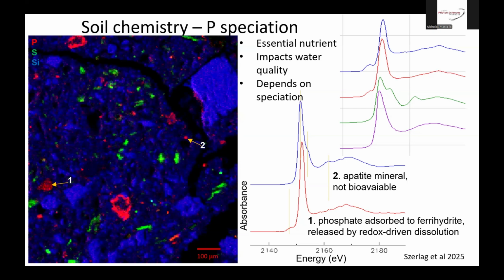So the grain marked 2 is the mineral apatite, so it's a mineral grain, so it's relatively inert, and it will not be bioavailable, and it won't wash away very easily. But the one labeled 1 is more diffuse, and that's actually phosphate adsorbed to ferrihydrite, an iron mineral. And you can see that there's a characteristic little pre-edge feature that's characteristic of iron 3+ phosphates, not iron 2+ phosphates, so it can actually tell the difference of that.